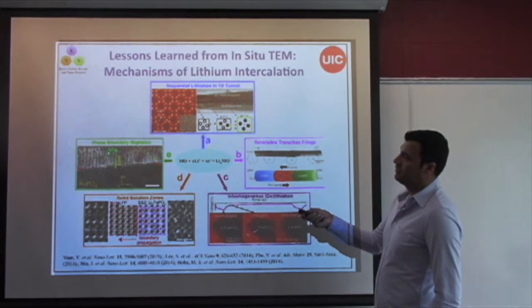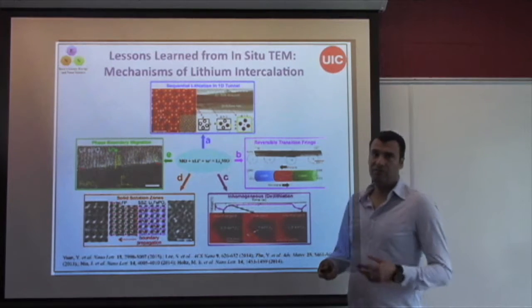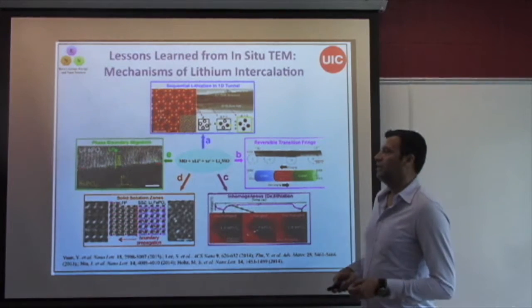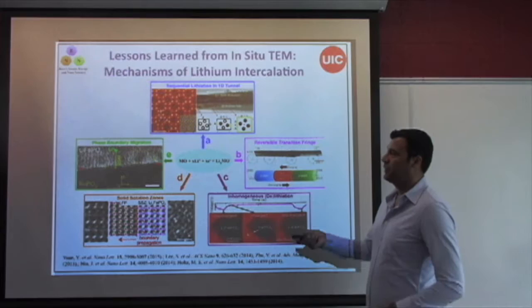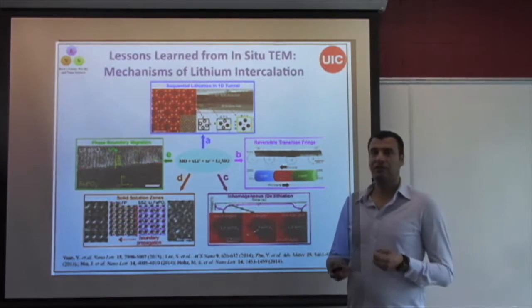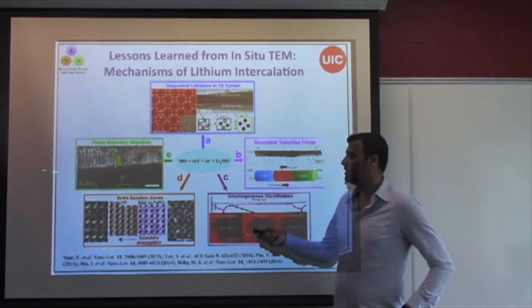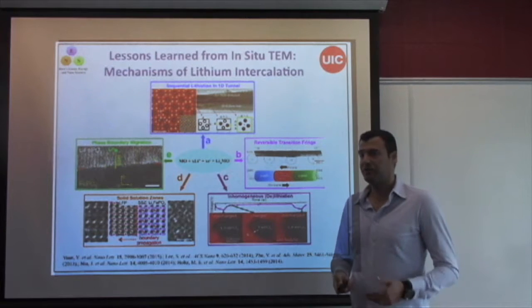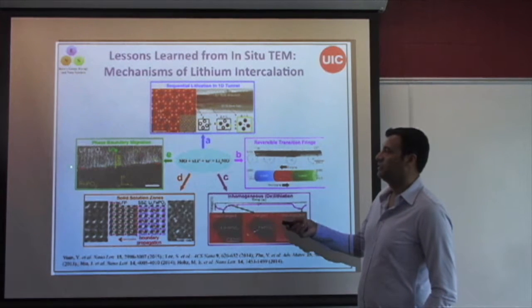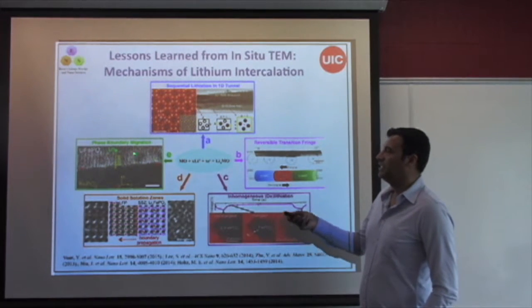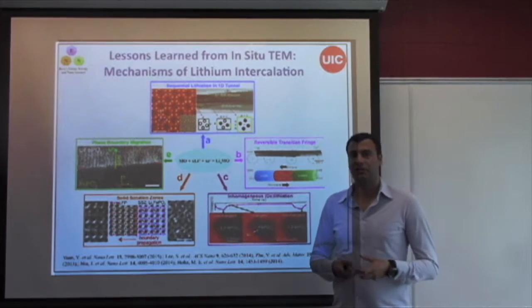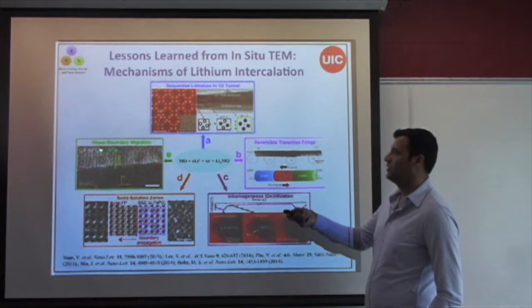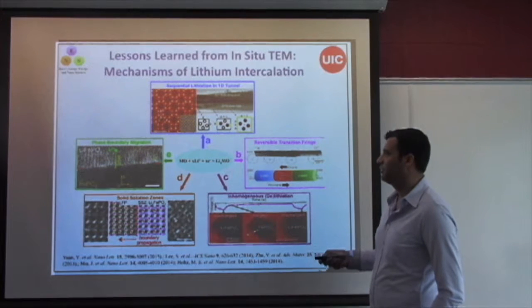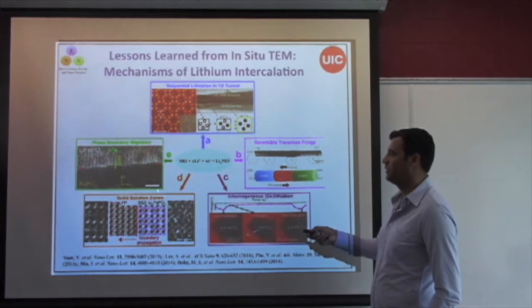The progress of the phase boundary between lithium iron phosphate and iron phosphate, and whether you have a solid solution or a two-phase reaction, has been a debate in the community for many years. This in situ work nicely showed the interface between these two regions. Later on you can look into this more if you are interested.